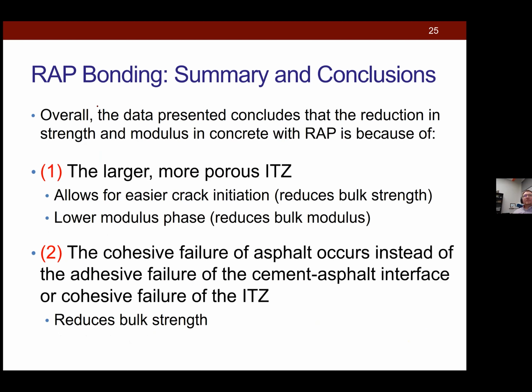All right. So what we're able to conclude is really the sources of problems with RAP were these two issues, right? That larger, more porous ITZ. And again, great. We found we could reduce the ITZ a little bit with silica fume. Not as good as if we did it with like a limestone or a granite aggregate, but we could improve it a bit. The problem was your cracks are still going to go through the asphalt film. Okay. So this right away should tell you that, hey, maybe we can't really think about concrete with recycled aggregates in the same way that we think of conventional concrete.